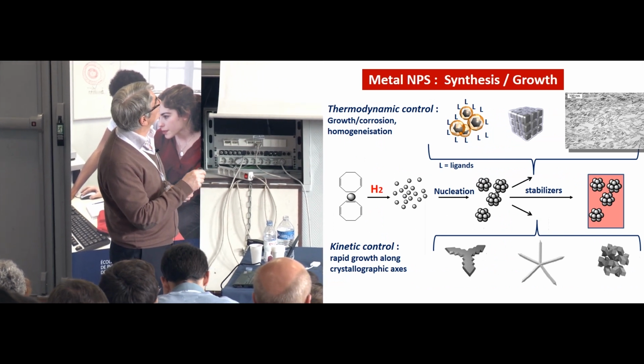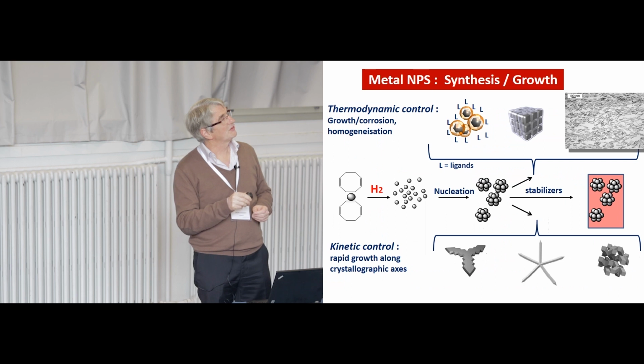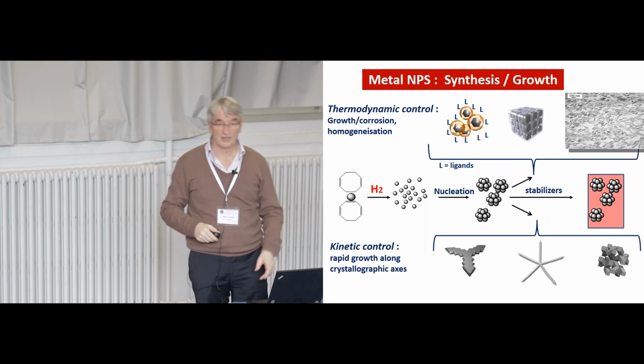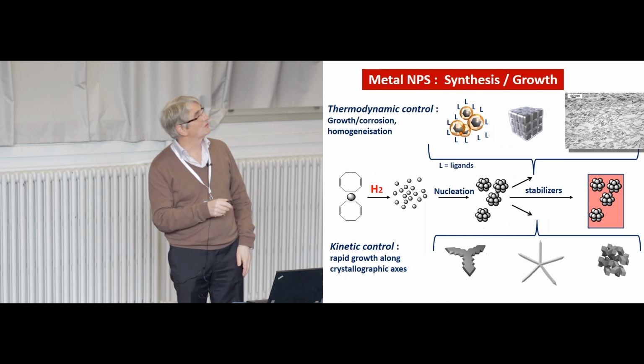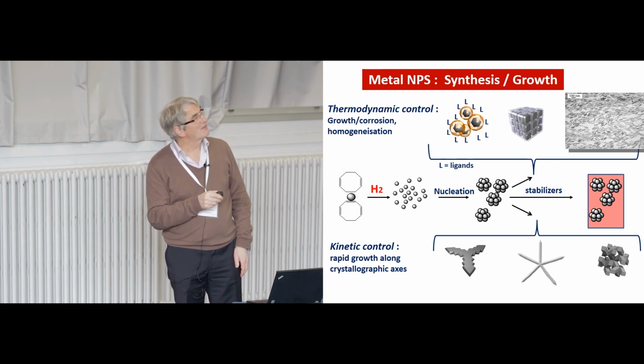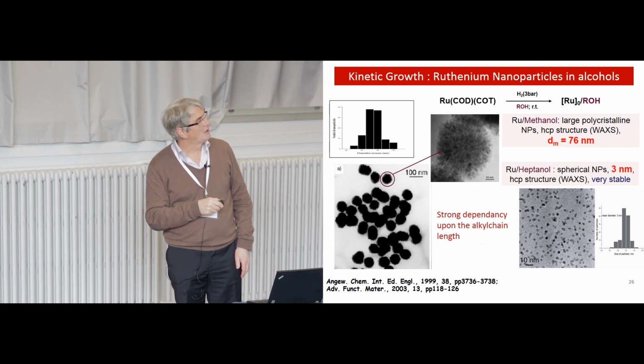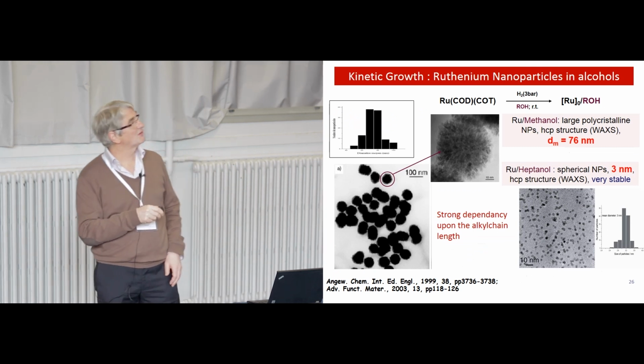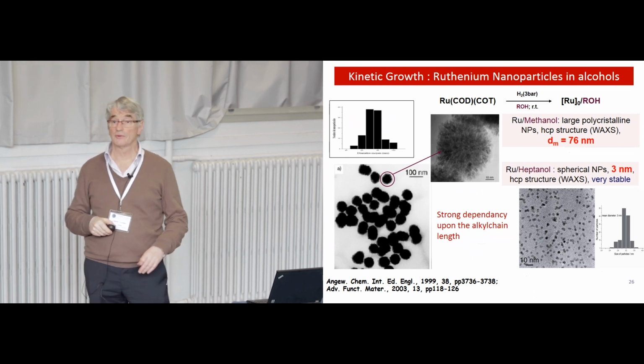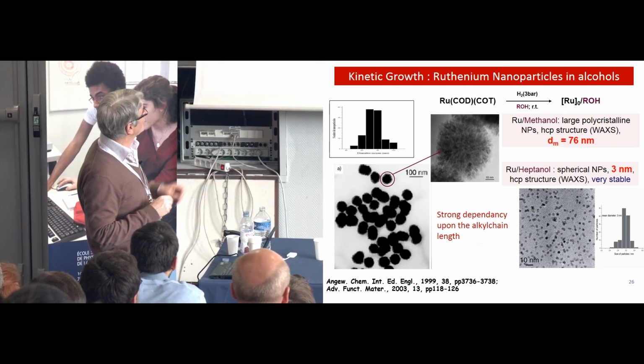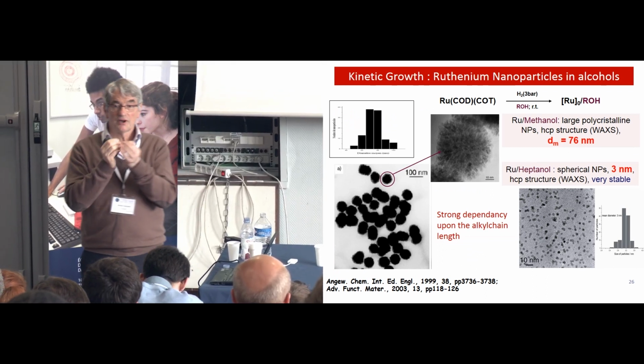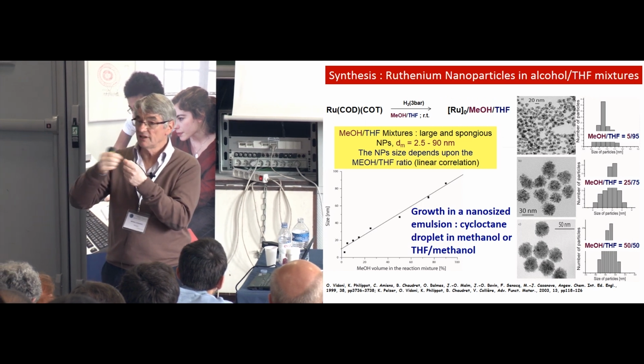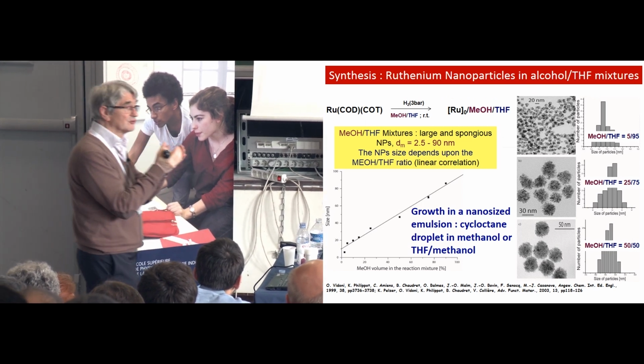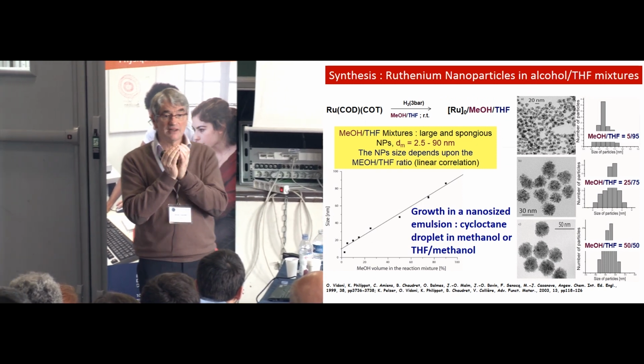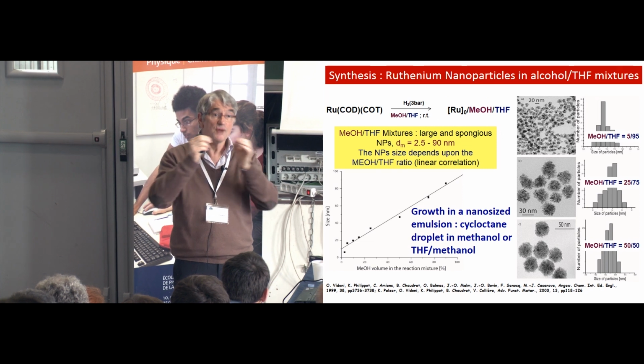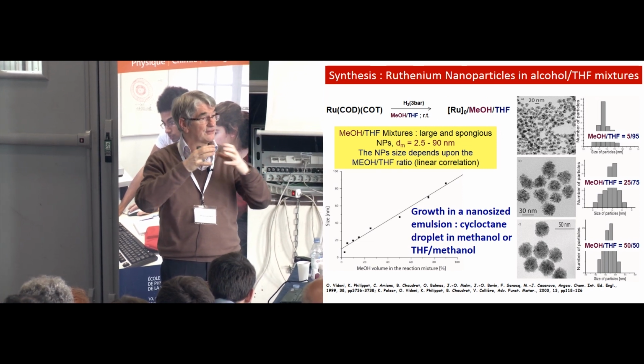We started to decompose Ru(COD)(COT) in the presence of an alcohol, and we saw large polycrystalline ruthenium. We also saw that in a methanol-THF mixture, we could control the size of the particle by the amount of methanol we put in THF, which we did not understand for a long time. But in fact, we have droplets of cyclooctane which form in the solution, and they control the growth of the particle. The only message here is that you don't need much to control the size, kinetically, of the particle.